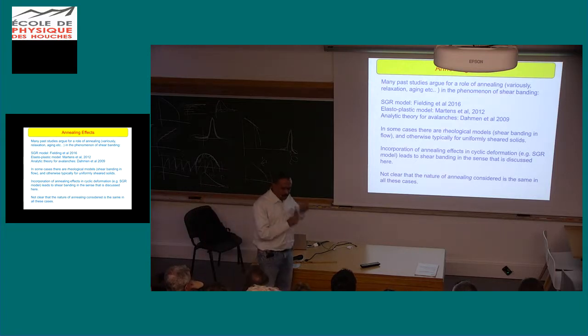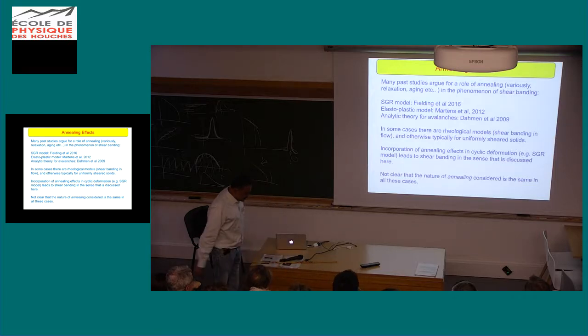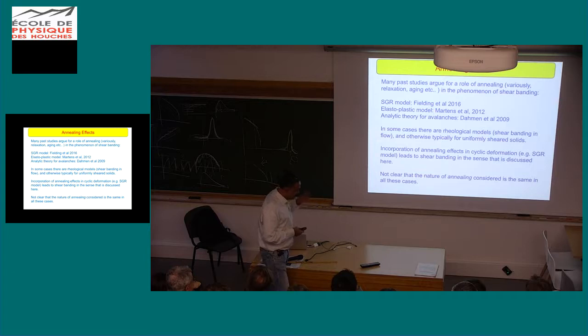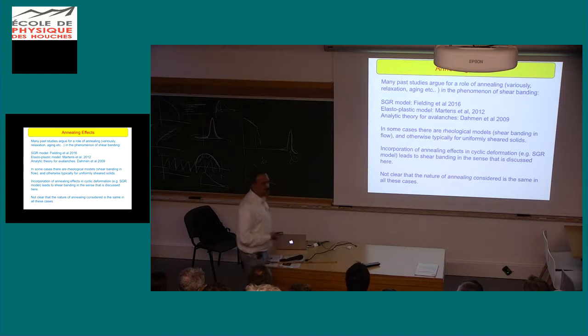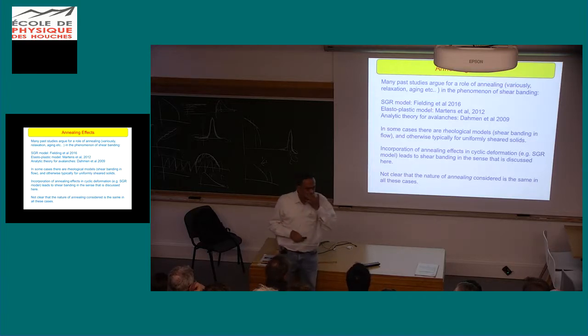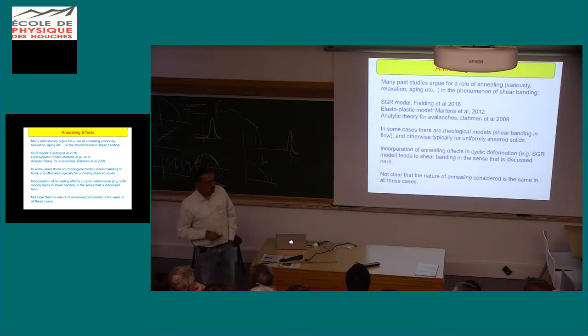And now, as you heard a little bit in the morning, the shear banding, not in the same sense, but in the sense of stable shear bands as you increase the strain, has been discussed by various people as arising from a competition between annealing and rejuvenation effects. The shear bands that we see in cyclic deformation have not really been analyzed very much, but as you will hear tomorrow, even under uniform shear, for very well annealed glasses, you see shear bands.